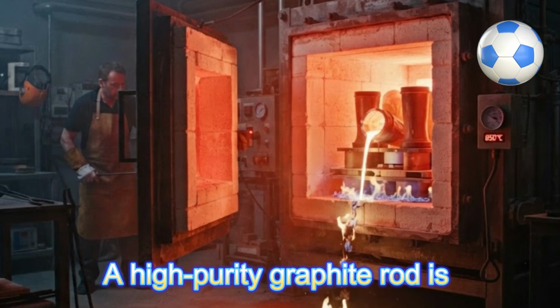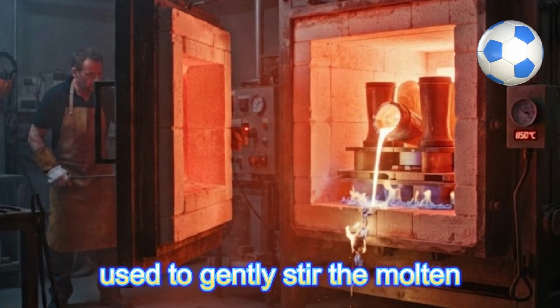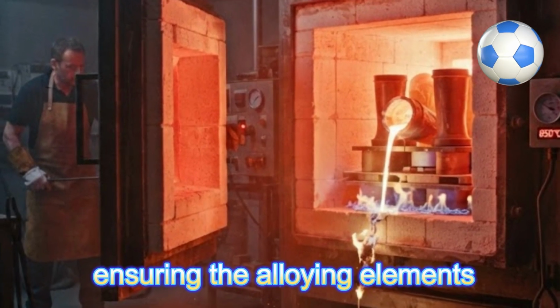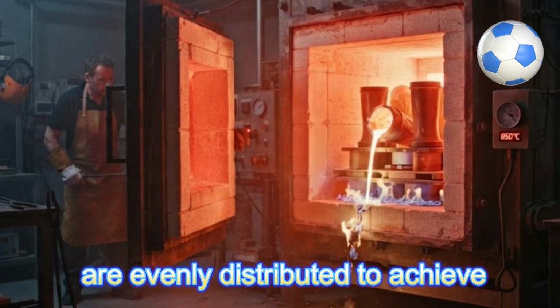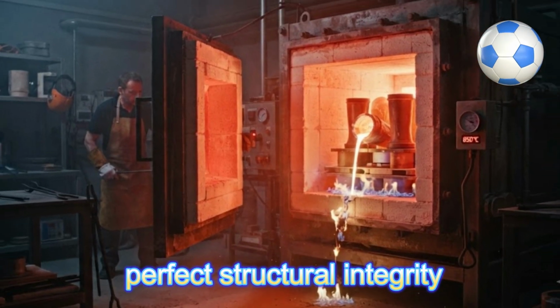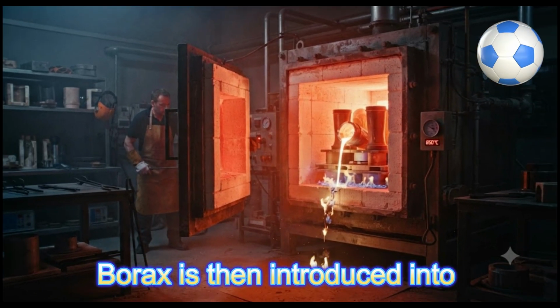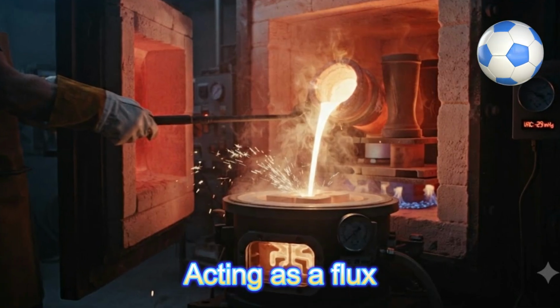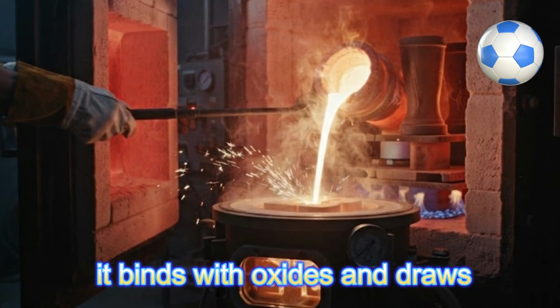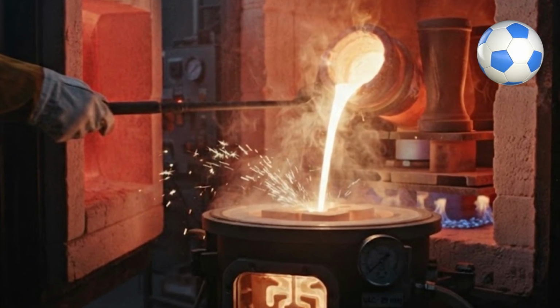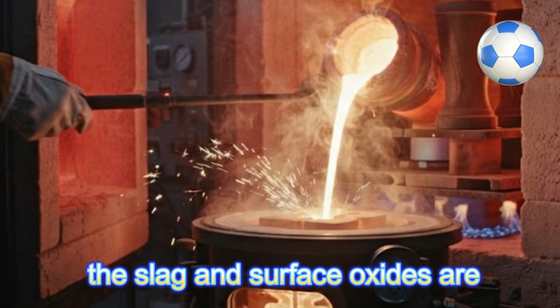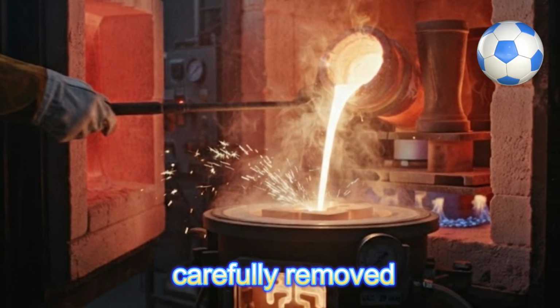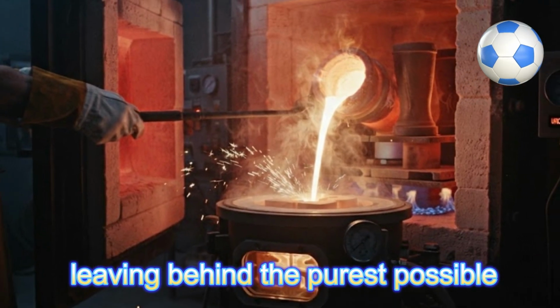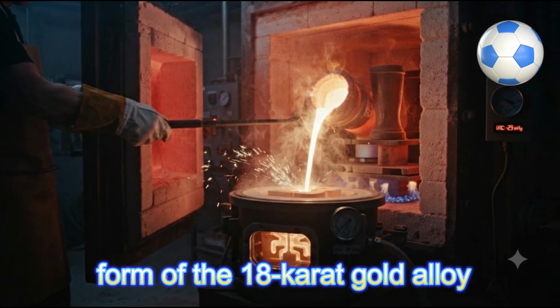A high-purity graphite rod is used to gently stir the molten metal, ensuring the alloying elements are evenly distributed to achieve perfect structural integrity. Borax is then introduced into the melt. Acting as a flux, it binds with oxides and draws impurities to the surface. With meticulous precision, the slag and surface oxides are carefully removed, leaving behind the purest possible form of the 18-karat gold alloy.